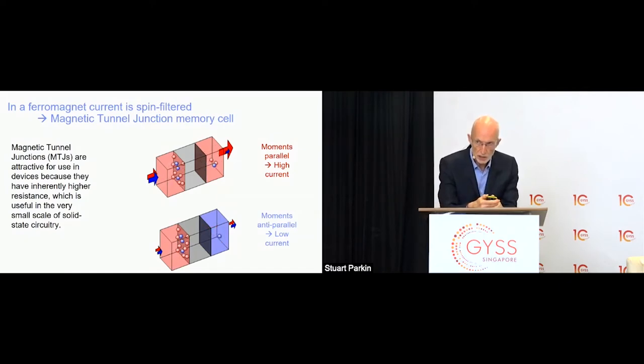Today, the difference in the tunneling current for these two orientations for interesting tunnel junction devices can be several times. So the tunneling magnetoresistance can exceed several 100%, even at room temperature. The metallic spin valve devices, even at room temperature, in the sandwich devices, the typical change in resistance is only 20%, but that still made them extremely useful to detect tiny magnetic bits. So the tunneling magnetoresistive devices, using exactly the same spin engineering principles I discussed earlier, are today the devices that are used in magnetic disk drives to read information.